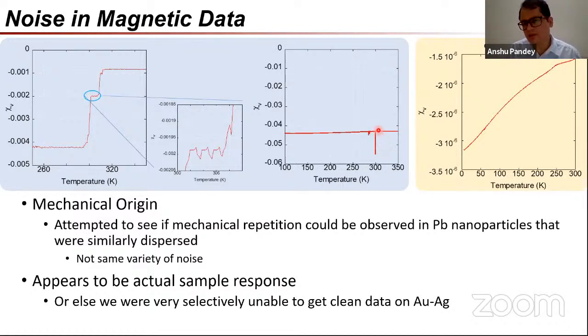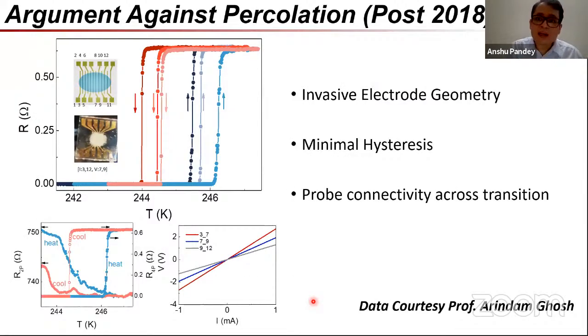These are all in the magnetic data for some reason, which also should not ideally be there, because earlier, in our very initial observations, we thought that maybe these are mechanical noise. We would try to discard such data and find alternative scans where we would not have this. But then again, this sort of thing does not show up in any other material. It doesn't show up for lead, and it certainly does not show up for any other sample. It appears as if these are actual sample responses, or maybe for some reason, because we don't know the nuances of this material completely, we are unable to get clean data. Regardless, this is where the noise issue stands. The arguments against percolation, I'm very thankful to Professor Arindam Ghosh for this data.